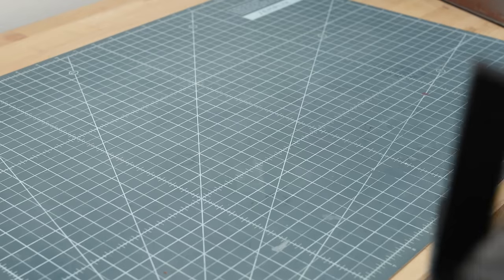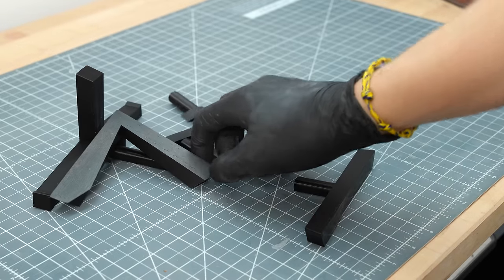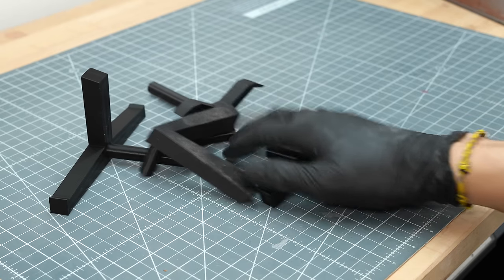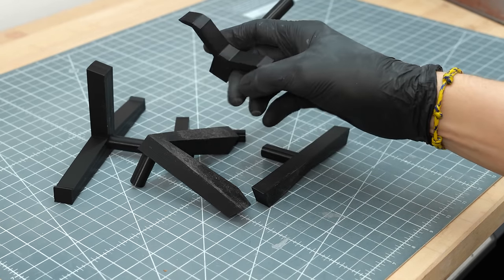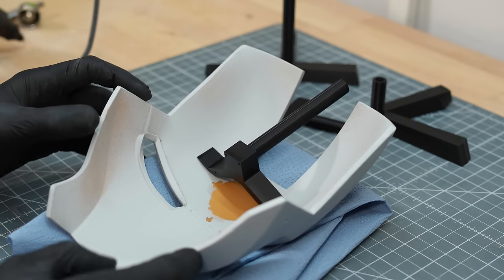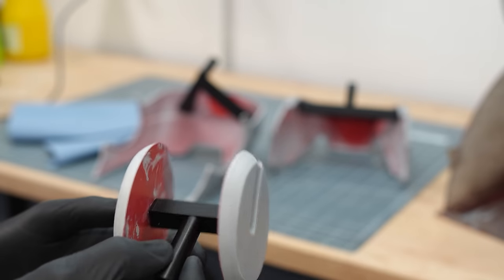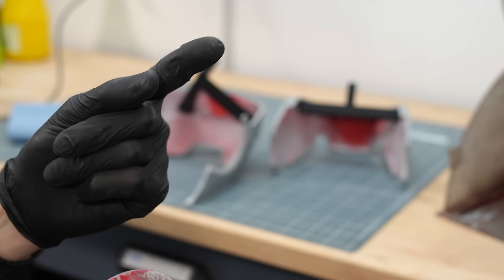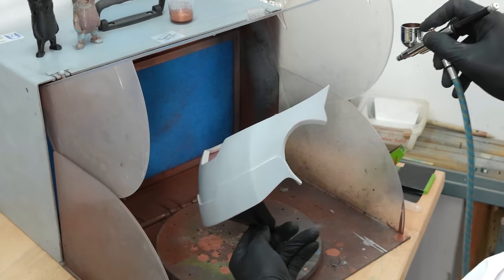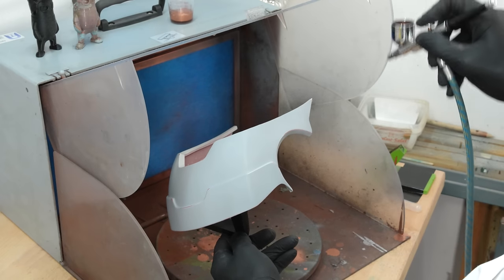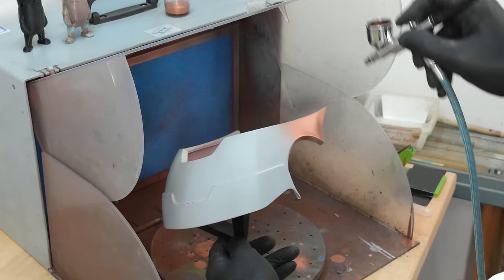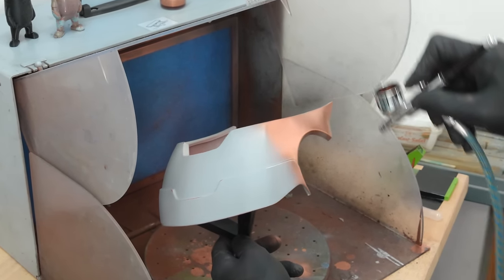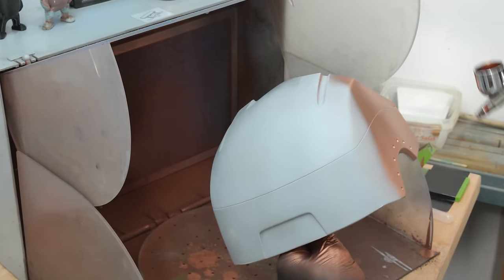I won't be able to hang the toilet paper rolls in the plating bath later, but the idea is good. That's why I designed custom part holders that I attach to the parts again with hot glue. This allows me to secure the 3D prints well during painting and plating. I spray around 2 bar. Make sure that the surface is completely degreased and clean, otherwise every hair, every speck of dust will be visible later.